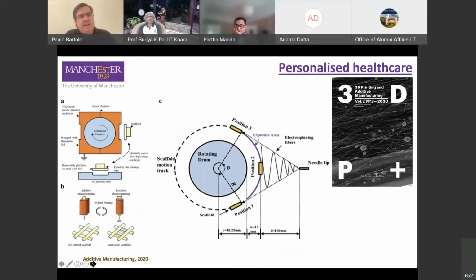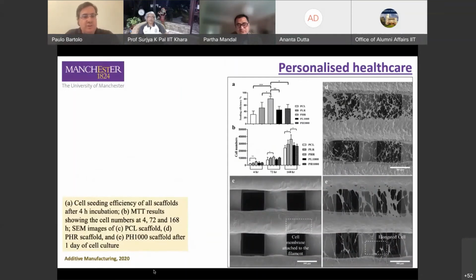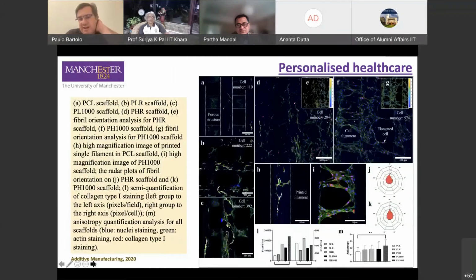To combine, and this is quite critical, good permeability and high cell proliferation, we are also combining different technologies. We are combining extrusion and electrospinning. Initially, and this was published in 3D Printing and Additive Manufacturing, we used a flat collector for the electrospinning. Then we published another paper where we use a rotating drum, which allows us not only to have a better control on the electrospun meshes, but also to increase the density of that electrospun mesh. So by combining these two technologies, we were able also to increase the biological performance of the structures. We also control the anisotropy of the cell distribution on the scaffolds.